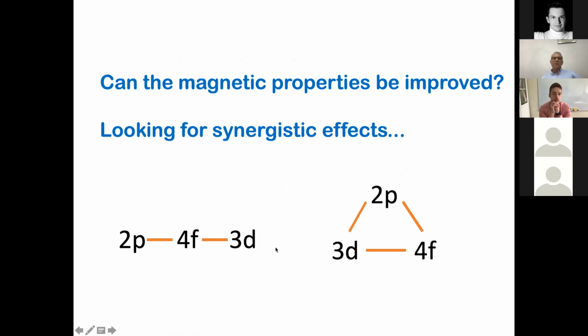And also the beauty of the synthesis has been illustrated from the magnetic point of view. It was a disaster because the 2p4f system, containing only 2 spin carriers, was a single molecule magnet, while the 3-spin system was not. So the next important step in our chemistry is to force the 3 spin carriers to work together. In other words, we are looking for synergistic effects between these 3 exchange pathways. And this is possible only having this topology.